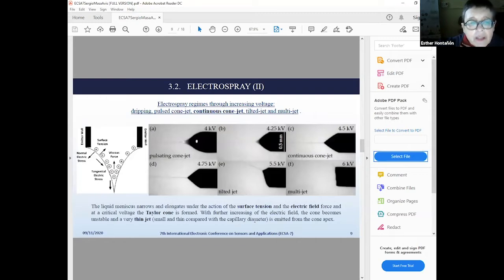Here you can see the different regimes that one finds once the feed rate of the dispersion is set to a given value and you start increasing the voltage applied to the needle. The electrospray grows through a variety of operation regimes and transitions, starting from a very highly unstable one, which is this pulsating cone jet, and then it reaches this more stable continuous cone jet mode. And by increasing the voltage further, this jet starts moving around the cone, and at some point you get this kind of tilting of the jet, and finally the atomization or appearance of multiple jets.